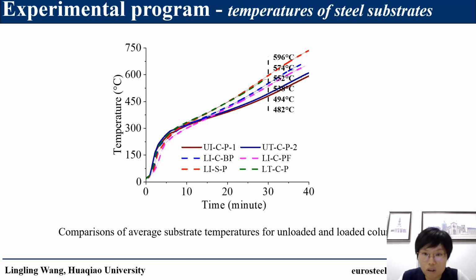According to the specifications, unloaded tests are used to calculate the effective thermal conductivity of intumescent coatings. Conducting fire tests on unloaded column and plate specimens is an economical method. However, in order to ensure that such results can be safely applied to loaded specimens, it is important that effective thermal conductivity results from unloaded tests are modified to incorporate the effects of cracking and debonding on intumescent coating behavior.